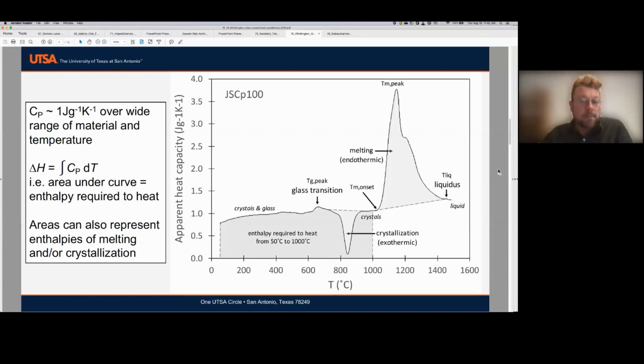Now, what will happen with something that was initially glassy like JSC is that the glassy part is actually going to crystallize, as we mentioned. But now we have something that can perhaps stick together. So this is basically sintering. And one thing we're going to look at is, can we make a brick by sintering glassy material rather than heating everything up all the way to the liquidus temperature, much higher temperature, and then cooling and crystallizing? Because that takes a lot of energy.